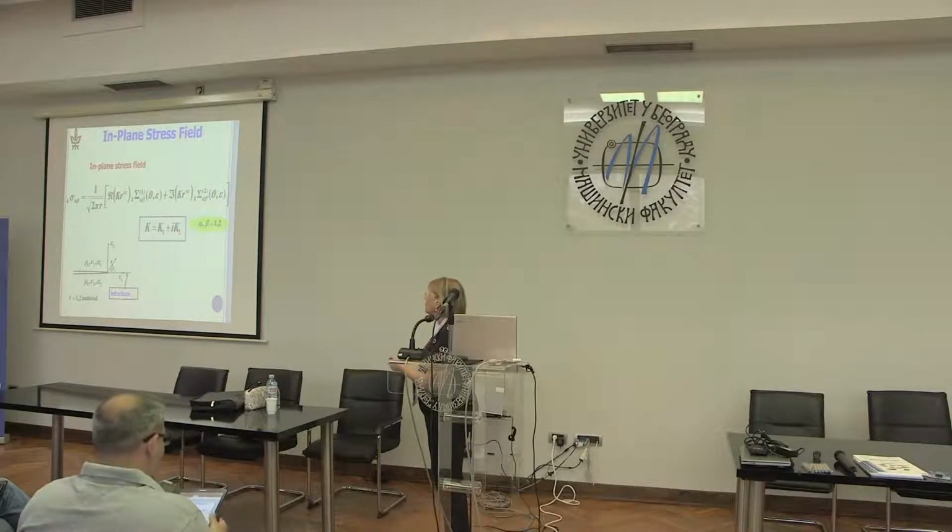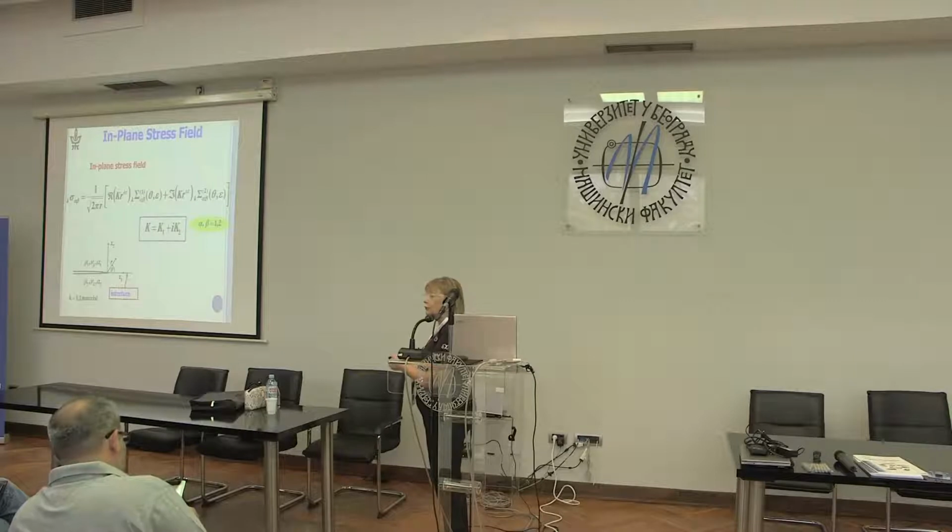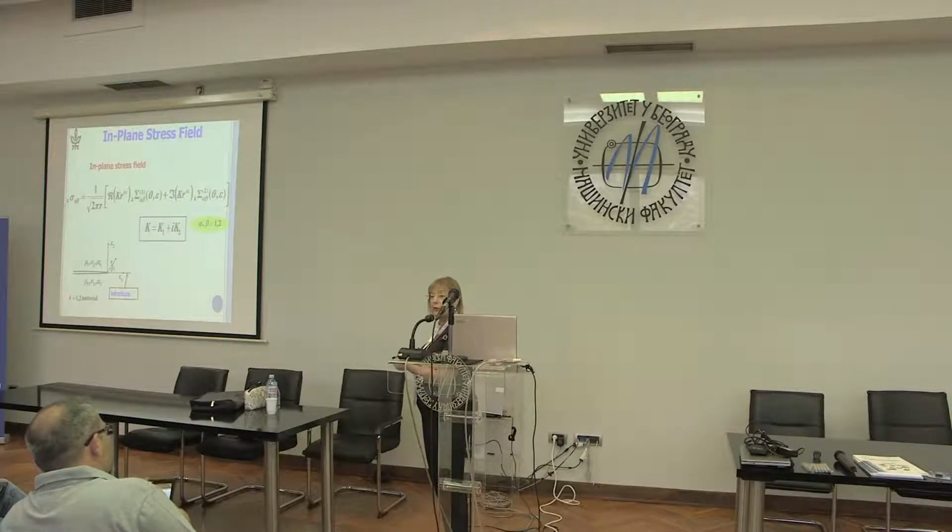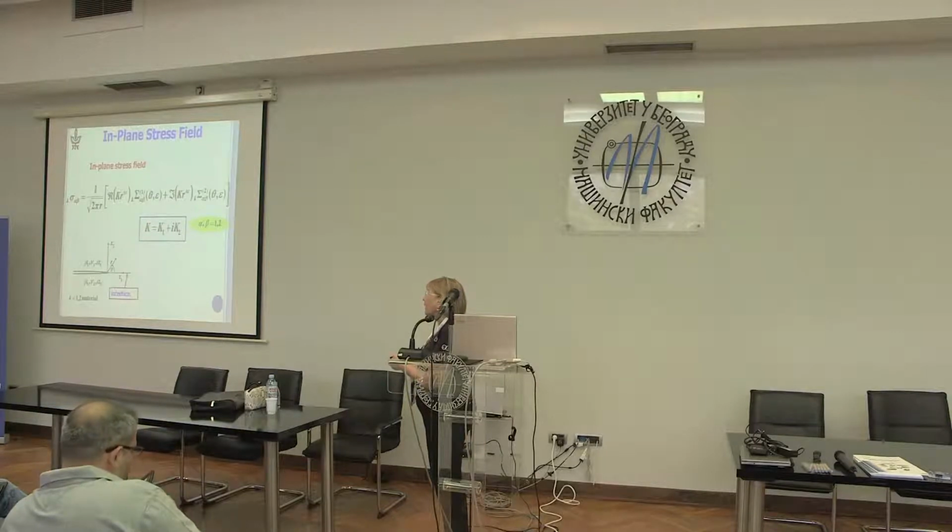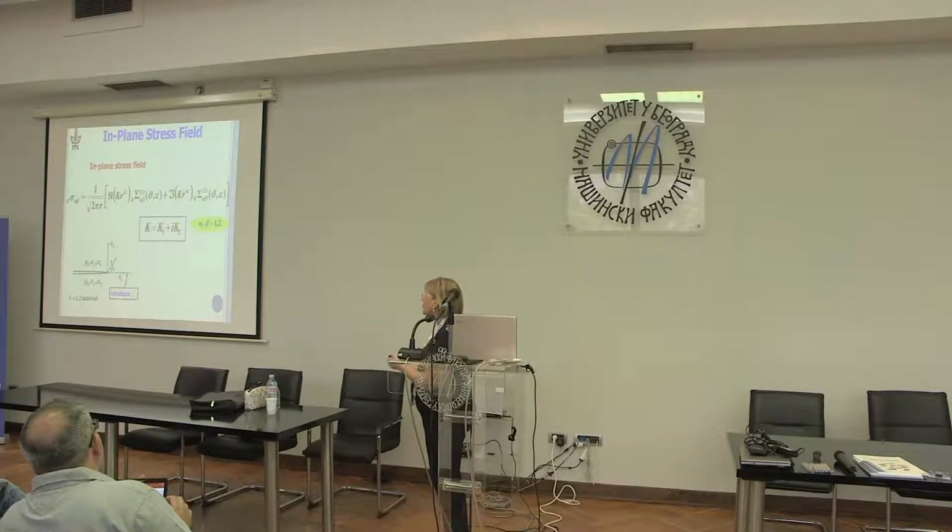And now we have something which may seem a little strange to people who know fracture mechanics and know about mode 1 and mode 2. We now have a complex stress intensity factor and they don't have the normal units that we know from isotropic homogeneous materials, and I'll say more about that as we go. So K appears in this expression and the second expression. This is the real part of this expression. This is the imaginary part of the same expression, and i is the square root of -1.